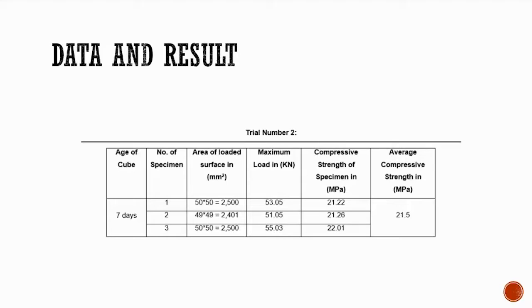In trial number 2, the age of the cube is also 7 days. There are also 3 specimens. The first specimen is 50 by 50, which equals 2,500, and that's the area loaded. Maximum load is 53.05. Compressive strength of the specimen is 21.22. Specimen number 2 is 49 by 49, which equals 2,401. Maximum load is 51.05. Compressive strength of the specimen is 21.26. And specimen number 3, area of loaded surface is 50 by 50, which equals 2,500. Maximum load is 55.03. Compressive strength of the specimen is 22.01. The average compressive strength of the 3 is 21.5.